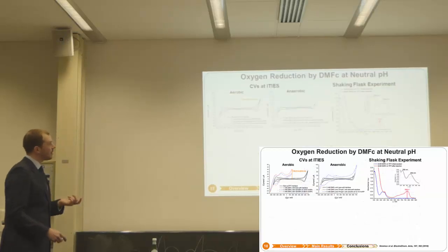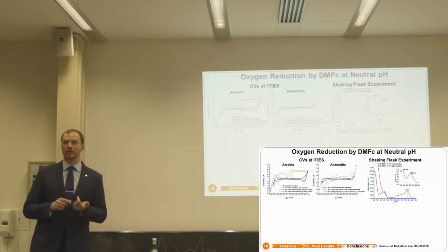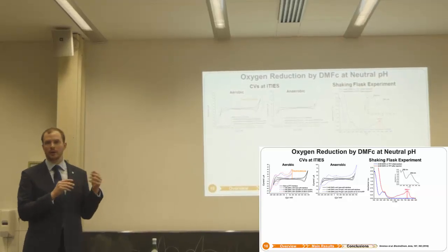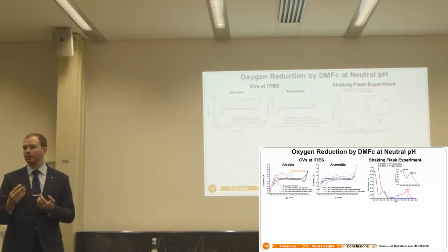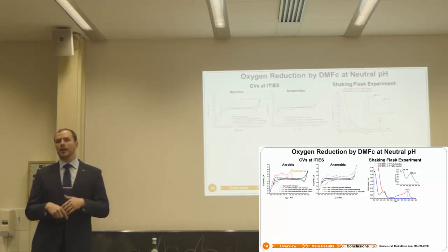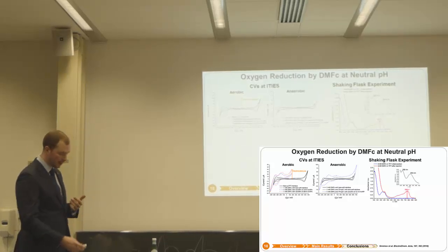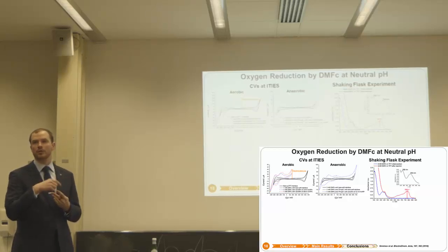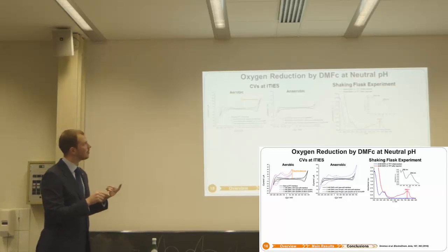And how do we utilize that? We utilize that for the oxygen reduction reaction at gold nanoparticles. In the previous slide, we saw that nanoparticles could be charged if we put some electron donors in one phase. And now I would like to show how they could be discharged into another phase. So nanoparticles are working as short cuts for electrons that can jump from one phase to another one. And we changed it to decamethylferrocene, which is a very strong electron donor.